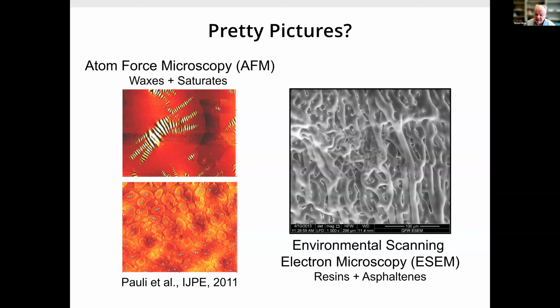On the right, in contrast, is an environmental SEM picture. We evaporated the oils; we did that at Queen's here. You can see the resins and the asphaltene molecules, which are the higher molecular weight molecules that form a brain-like structure. There's no wax in this binder because it's a good quality crude from Alberta. But what I want to show with this picture is that there is a structure underlying this flat, shiny asphalt binder, and that structure takes time to equilibrate. It takes time to form, and in the winter, it can stiffen the asphalt binder and inhibit flow at low temperature, and therefore accelerate the cracking.